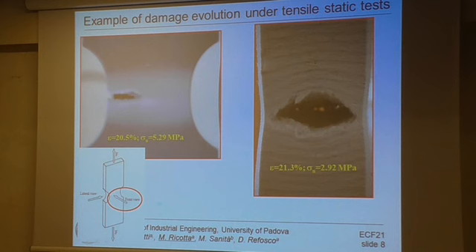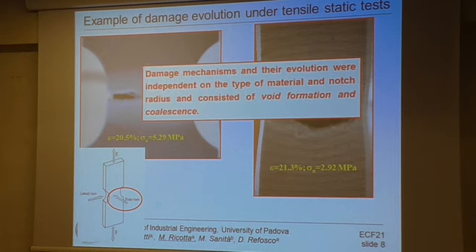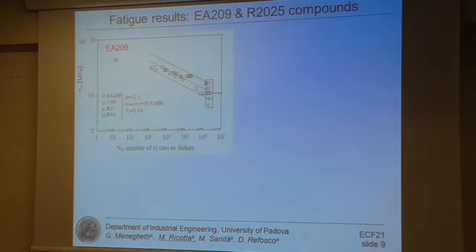Otherwise, if we observe the specimen from the front view, we can see that the final crack has not completely propagated yet in the net section. We have performed this type of analysis for all the materials and for all notch radii, and we can conclude that damage mechanisms and their evolution were independent of the type of material and notch radius. They consisted of void formation and coalescence.